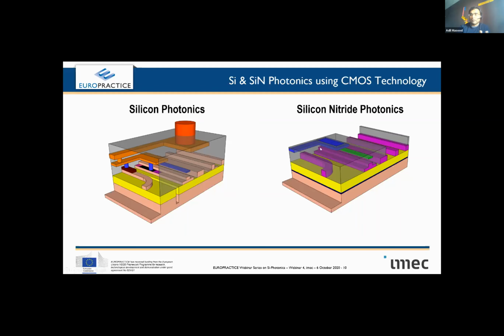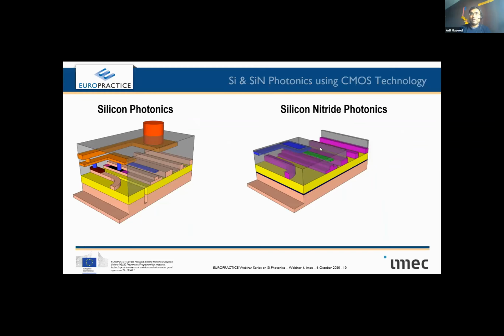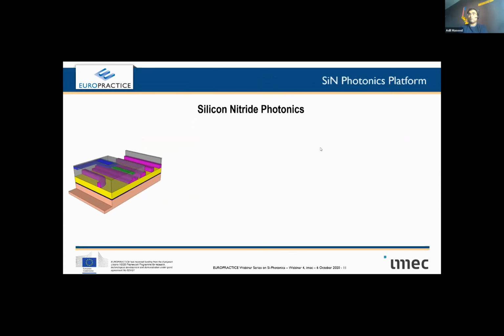Usually, okay, let me move to things one by one, so that I do not cause more confusion than what I have already caused. Okay, silicon nitride photonics. Going back to the stack, now we can go step by step what it has. The lowest layer is actually silicon, followed by a thin layer deposition of some anti-reflective material. That's the choice. And then oxide. After that, a silicon nitride layer is deposited.